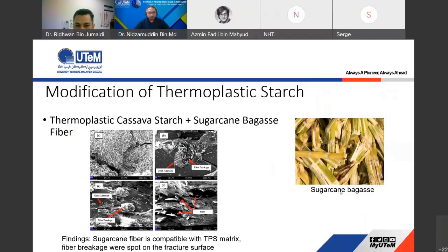In this study, I'm going to share some pictures. We're using sugarcane bagasse, which is a waste from the production of sugar, as everyone knows. As you can see here, the sugarcane bagasse fiber is in extremely good contact with the thermoplastic starch. It means that this fiber and the thermoplastic starch have good compatibility, so they can support each other. Unlike most previous studies, which used synthetic polymer as the polymer matrix, we cannot see this kind of interaction with synthetic polymer, because of the difference between the hydrophilic nature of the fiber and the hydrophobic nature of the polymer matrix. So this is one of the findings that we found throughout our study to develop these materials.